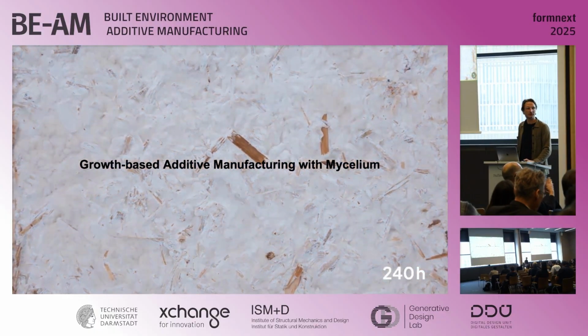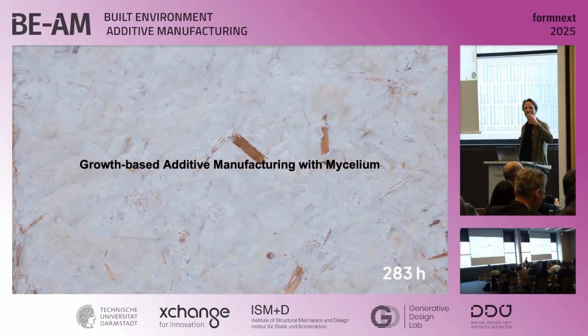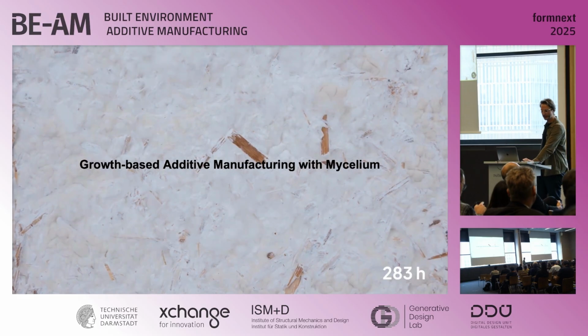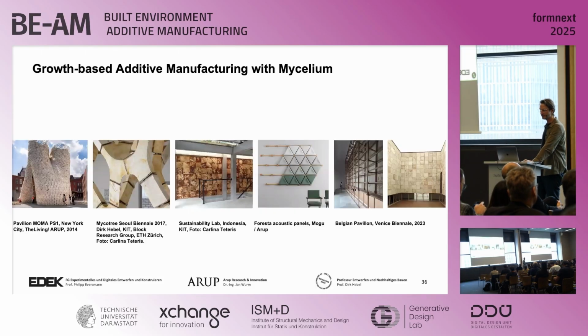It's the root network of fungi. Before the mushroom comes out, there is the root network, a really fast-growing material. If you compare that to timber, you have around 35 to 70 years until you can use it, whereas mycelium grows in large components in just 1 or 2 weeks. I always say it's like the light speed for a construction material, super fast. And you can also change the growing conditions, and that changes the material properties. So it's quite interesting, and it has really been a hot material in the past years.